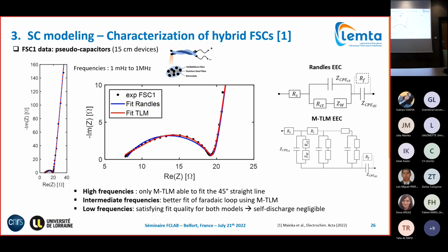Thank you so much. Sorry for bothering you midway, but I have a quick question. What happens if our slope is less than 45? I don't understand the physical meaning behind it, because that slope usually shows the diffusion process, even in fuel cells and batteries. I work specifically with batteries. In lithium batteries, that curve shows diffusion taking place at a very slow rate, which is why at lower frequencies we use it to describe that physical phenomenon. But when I use my curve, I'm not able to fit it at 45 degrees. My instinct was to use a CPE instead of a Warburg element, but it is still not giving a good result. So would you suggest using a resistance in series or in parallel with it?